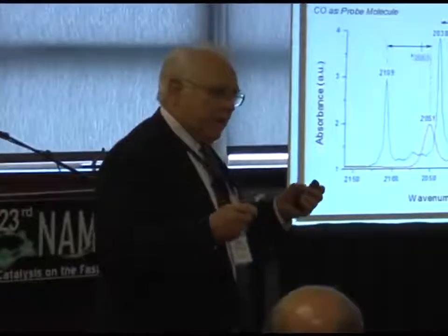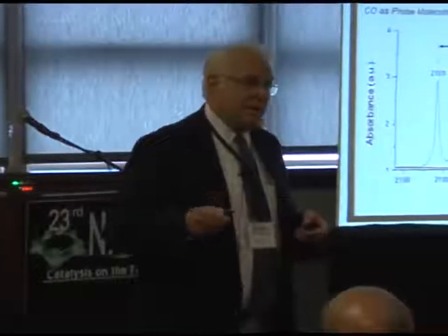And no, the zeolite's not perfectly crystalline, but it's close. And you contrast that with the broader peaks characterizing the iridium dicarbonyl on MgO, and you see broadening because the surface is not perfectly crystalline, there are defect sites. So there are various sites, and the classic surface heterogeneity that we all know about shows up.